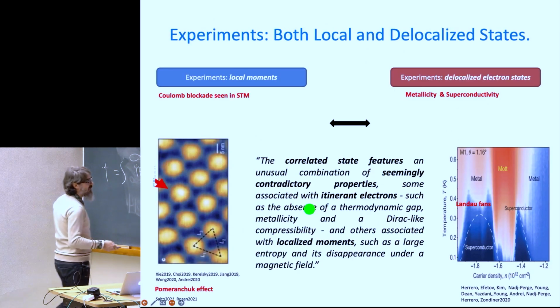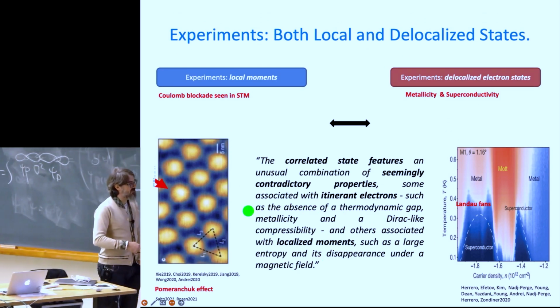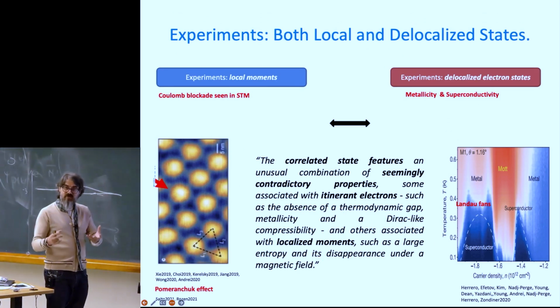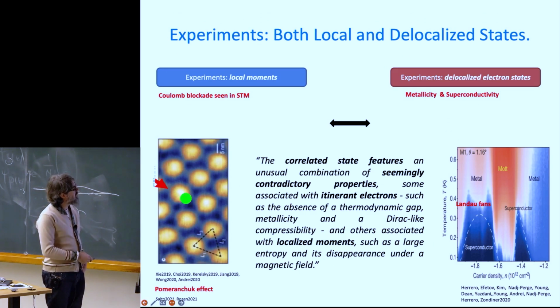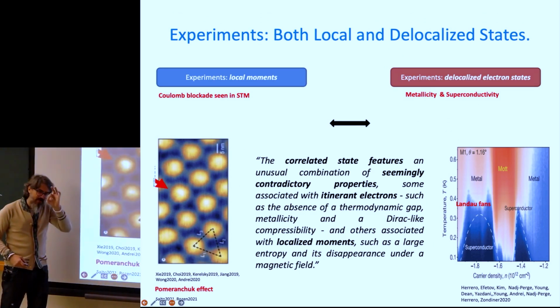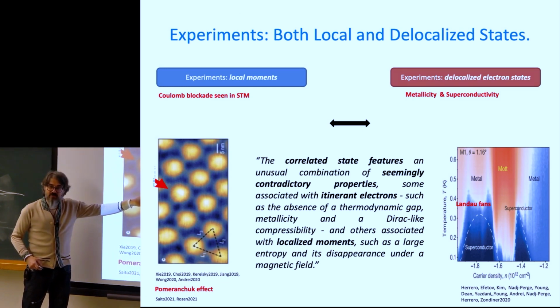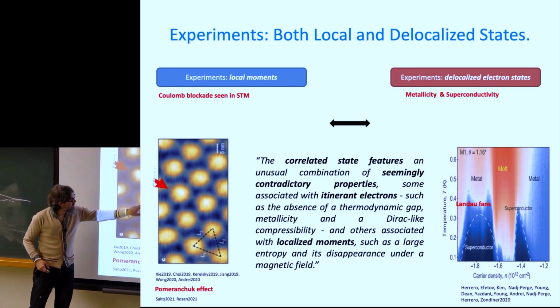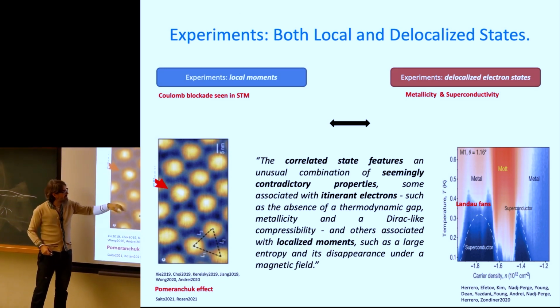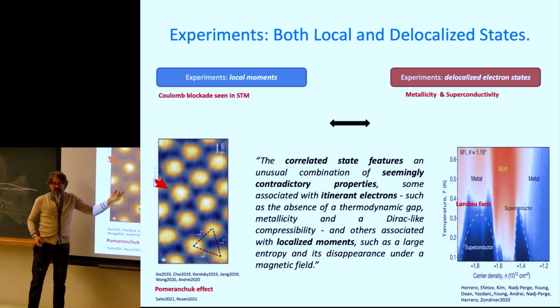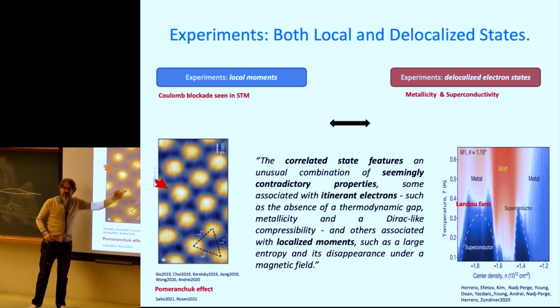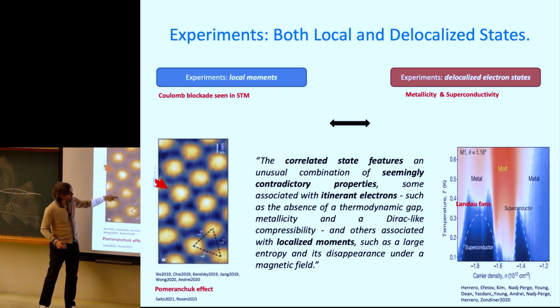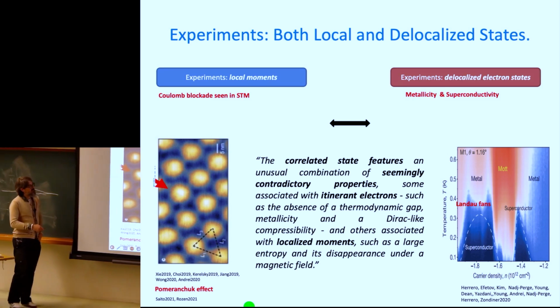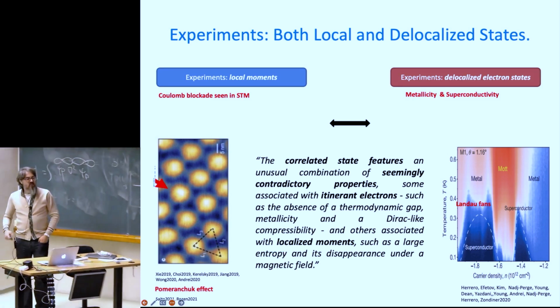But if I look at the picture given by STM, these are just like quantum snapshots of the electronic structure. This is the Moire unit cell. If you look, you can see an internal structure. That's the graphene lattice. You can clearly see some dots. There's the initial graphene lattice, but this is the Moire scale. The initial graphene lattice is angstrom size. This is nanometers. So about 10,000 or 8,000 initial unit cells in basically this unit cell here. This is the Moire charge density.